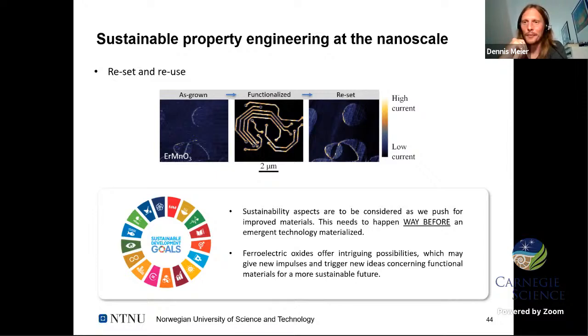That's why we also had to try all the different techniques to see the effects, because I think a vacancy causes in the manganites an expansion, an interstitial a contraction, and so the effect on the lattice compensates. It must be there, but if you have both sitting 6 Angstrom away from each other, we don't resolve that. So that's why it was so hard to track it down.